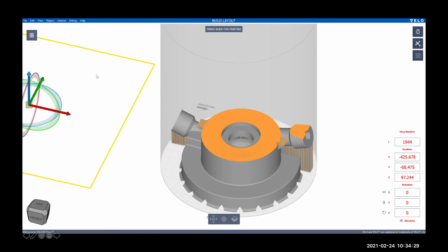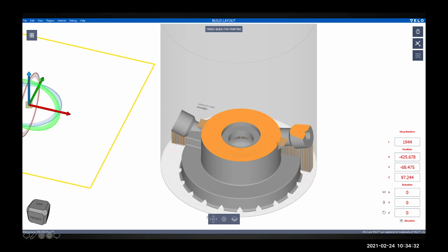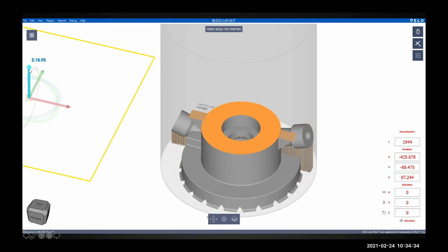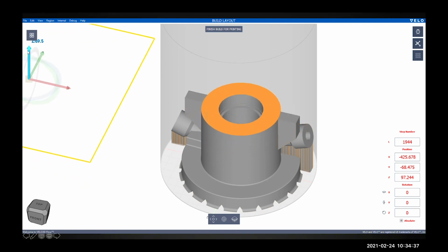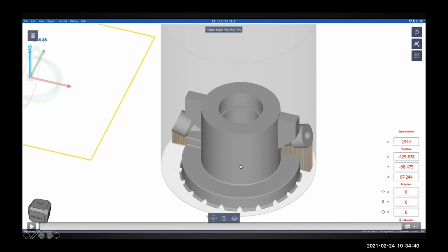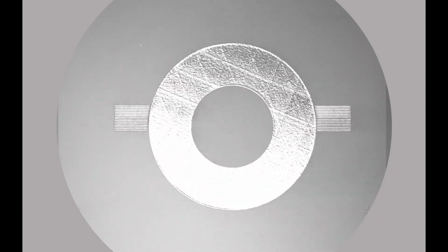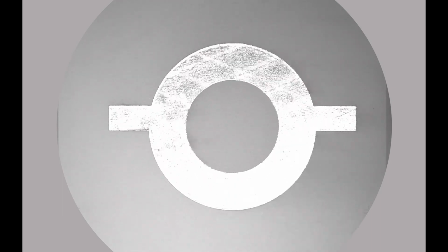So we print upward into the bulky section of the part, and that is where speed is the biggest winner. Being able to apply our 1 kilowatt lasers to this process enables us to print this part very quickly and effectively without any of the lack of fusion porosities or voids that would degrade the material properties. Here's a video. This is right from our height mapper structured light scanner, showing the entire print from start to finish, layer by layer, showing the volute sections, the closeouts, and then the bulkier sections that print with this high power 1 kilowatt process.